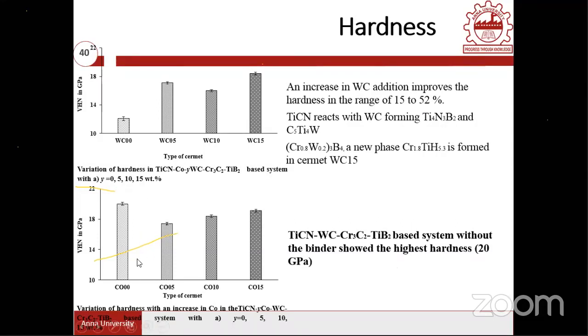And also in the cobalt addition, when you have cobalt ranging from 5 to 10, but here, if you look at this value without cobalt addition, but you have other elements like TiB2, TiN, but the cobalt is missing in the CO00, where it is giving more than 20 GPa value. But among all the tool compositions we have developed, without cobalt addition giving a good hardness value, but the toughness is really a problem.